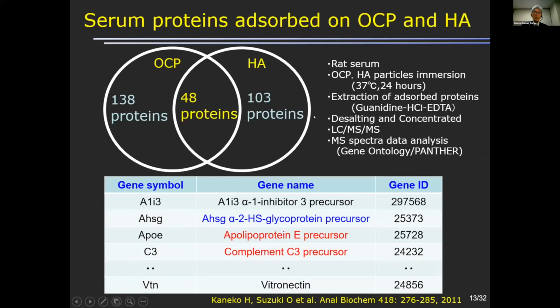We investigated the adsorption of serum proteins by incubating OCP or hydroxyapatite granules in rat whole serum and extracted adsorbed protein via guanidine HCl, which means that calcium binding proteins can be collected. And we analyzed them by liquid chromatography tandem mass spectroscopy to identify the adsorbed proteins. 138 proteins were detected on OCP and 103 proteins on HA, and 48 of which were common proteins. This table shows the common proteins, and we see the alpha-HS glycoprotein, apolipoprotein E precursor, ApoE, and the complement C3 protein.